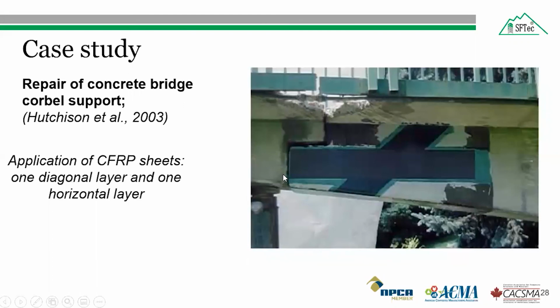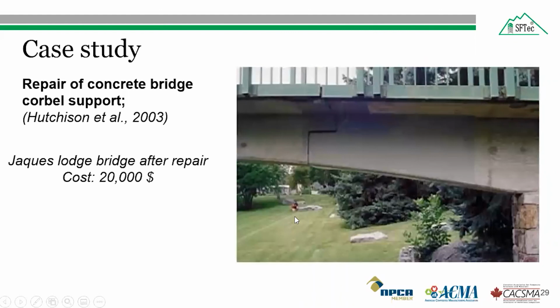Therefore, a strut and tie model was used to design the carbon fiber strengthening scheme. A single horizontal layer and a diagonal layer of carbon fiber sheets were applied on each side of the corbel, and you can see this bridge has been supported here. So this support was removed once the curing of the carbon fiber sheet was completed, and a protective coating was applied over here. The total duration taken for the repair was around 6 weeks, and it cost around $20,000.